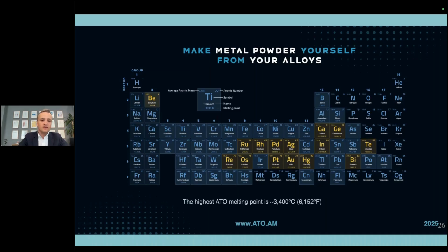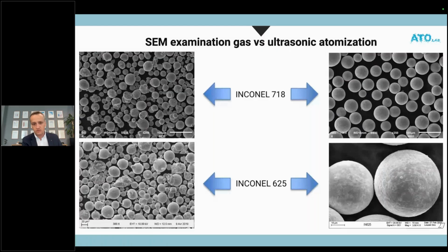And you need to know the biggest difference between the ultrasonic atomized powder and classic gas atomized powder. The biggest difference you can see in those pictures. On the left-hand side, you can see the powder atomized with the classic gas atomizer, and on the right-hand side, you can see our powder from the ultrasonic technology. How does it work? The biggest difference is in the production. Whenever we are speaking about gas atomization technology, we need to be aware that the powder is created by high-pressure gas nozzles, which turn the liquid material into a powder form. That's why in many cases you can observe satellites, which results in much worse flowability and powder quality.